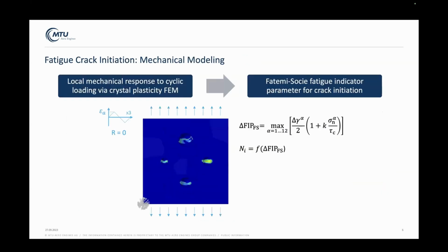So the way we are modeling this is using a micromechanical approach. What we're doing is calculating the local mechanical response using crystal plasticity simulations. And from the result of those simulations, we can derive a quantity called a fatigue indicator parameter that we are able to correlate to the lifetime. It is a field quantity, so we get it for every material point. And by looking at the largest of these fatigue indicator parameters in our configuration, we can determine the lifetime of that configuration.